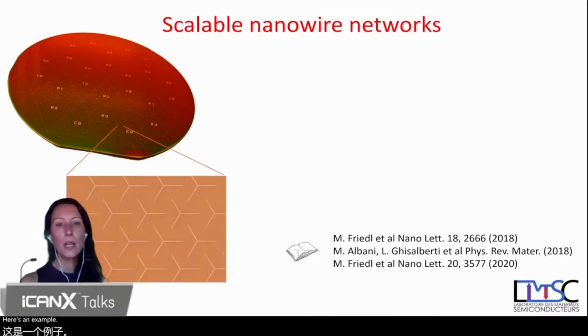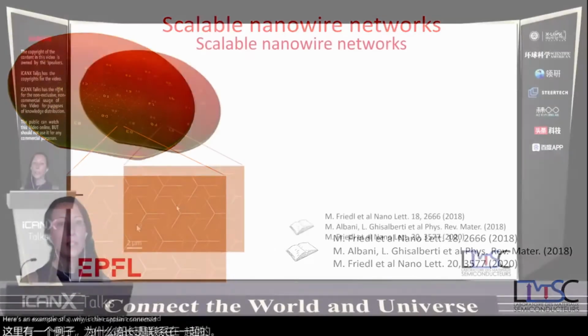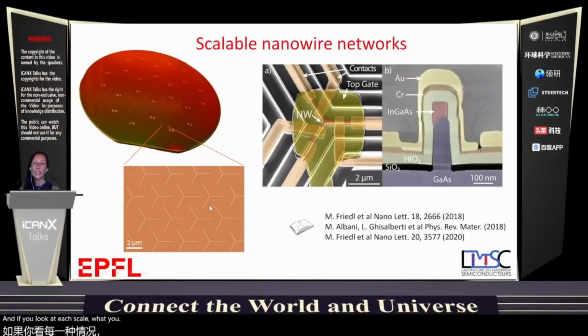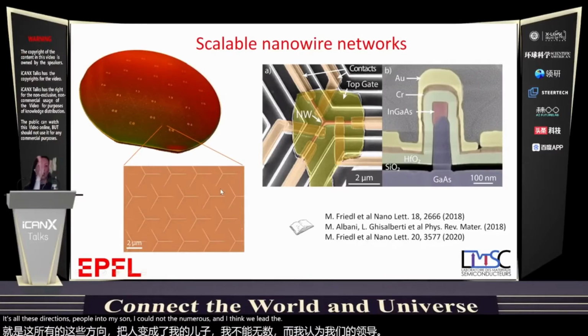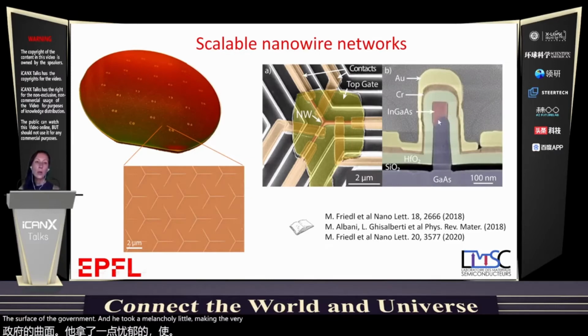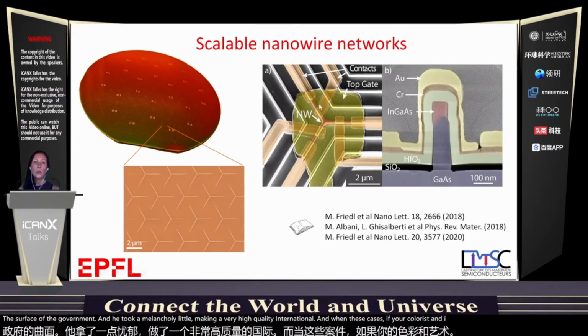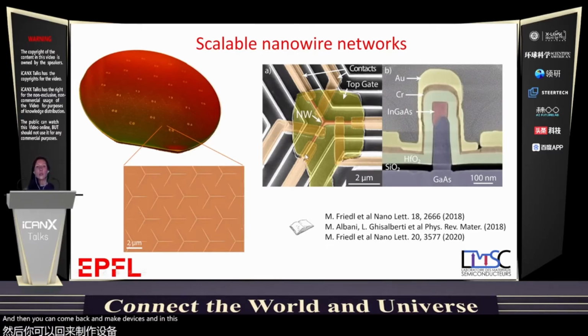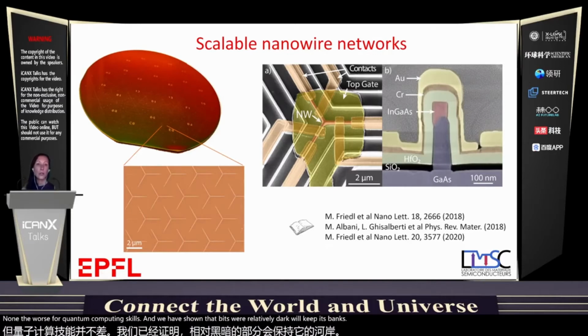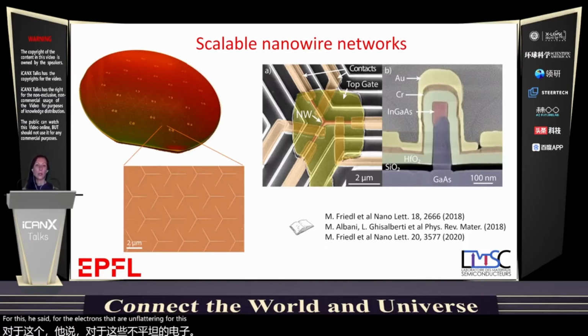Here is an example of wires that have been connected in this way. And if you look in detail, what you see is that we can grow indium arsenide, like this is gallium arsenide in all these directions. We grow indium arsenide on top. The indium arsenide will go right at the top, doesn't like to wet the surface of the gallium arsenide, and it accumulates only at the top, making a very high quality indium arsenide nanowire. In this case, it's an indium gallium arsenide nanowire. And then you can contact and make devices. And in this case, we have used these nanowires for quantum computing schemes, and we have shown that we have a relatively long coherence length for the electrons that are flowing through these nanowires.